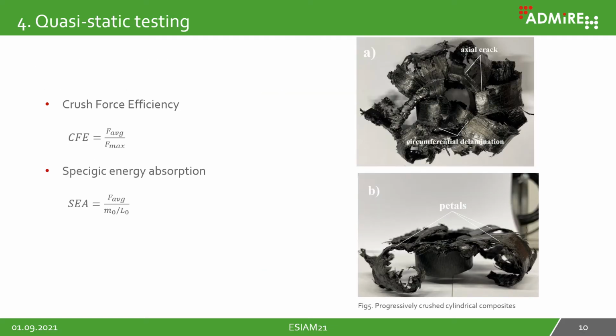The efficiency of the crash tube during the quasi-static compression test is determined by the crush force efficiency. This is the ratio between the average crushing force and the maximum crushing force. The specific energy absorption capability is determined by calculating the average load over the crush distance per absorbed mass of material.